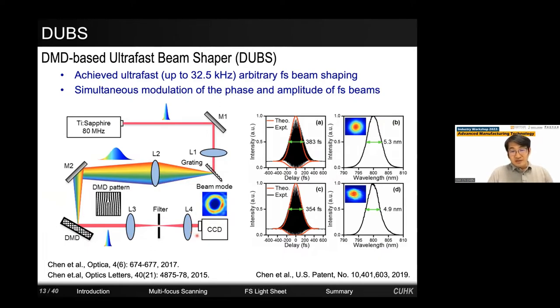Some people may wonder how come this was not done in the past. The reason is that for the longest time, the DMD was considered not compatible with the femtosecond laser because the pixels on the DMD are too small, which causes dispersion. We address the issue with this dispersion compensation design, as shown in the US patent here. And as a result, when we measure the pulse width after the DMD, it shows a very narrow pulse width and the diffraction effect has been entirely removed.